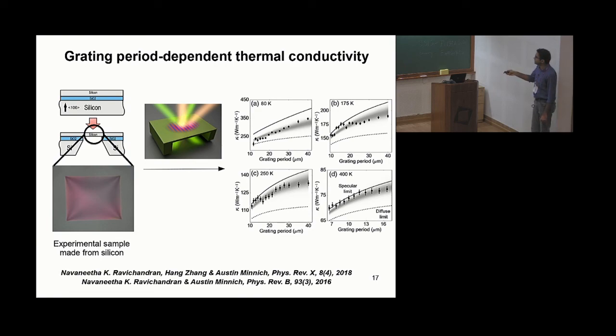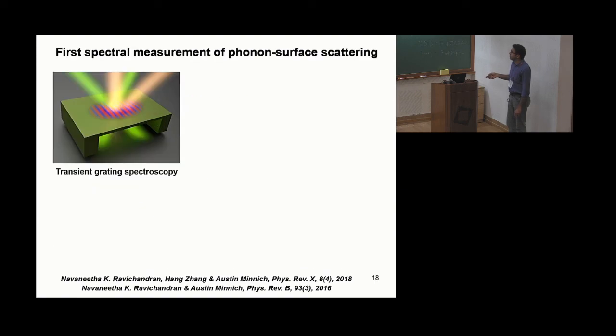As you can see, when I go from 40 micron grating period to 10 micron grating period, the thermal conductivity is dropping down. Fourier's law actually says the thermal conductivity should be length independent, but what we are seeing is the thermal conductivity is strongly dependent on length because fundamentally it's violating Fourier's law's assumption.